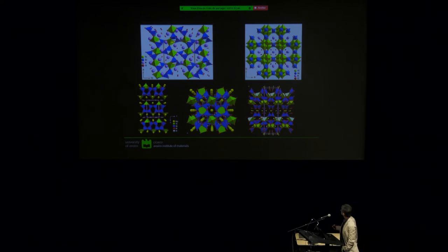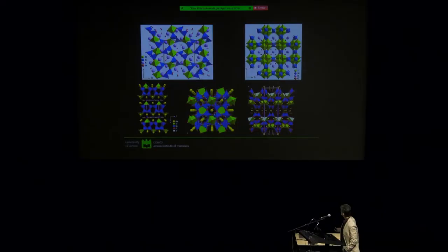And you can see that sometimes the polyhedra are isolated. Sometimes you have clusters. Sometimes you have layers, so not only framework materials, but also two-dimensional materials. And in some cases, something in between. For example, this material has perforated layers. So it's a layered material, but with sort of channels running perpendicular to the layers, and all sorts of different types of layers, complicated layers, and so on.